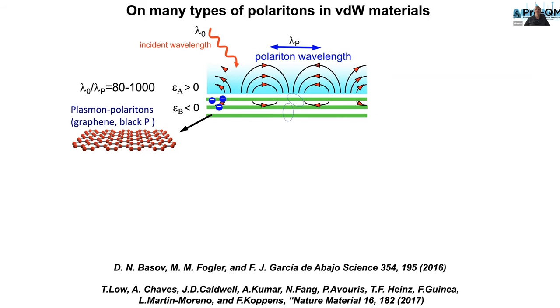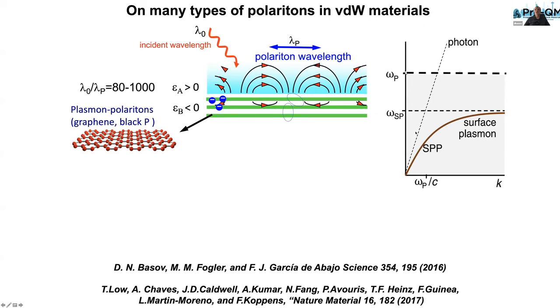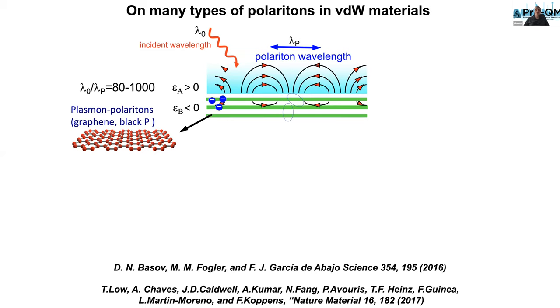These polaritons are very compact in van der Waals materials. This is a dispersion that I think this community is also very well aware of. So at reasonable frequencies where the surface plasmon polariton is still far away from the photon line, this confinement can easily be as high as 2 orders of magnitude, and in some special cases, even 3 orders of magnitude. So these are compact but propagating modes. So you can harness these modes to study new physics of a medium supporting these plasmon polaritons, and that's what we are doing routinely now in our experiments.